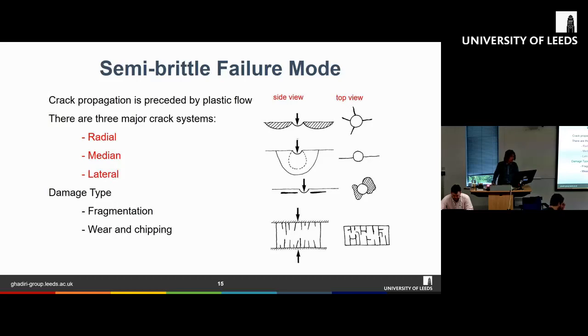And the third type of crack system is called the lateral cracks. Basically, this type of crack is on a surface which is parallel to the free surface of the material, and they chip off and come off from the surface. From the top, it's going to look something like this. Basically, thin layers of material will come off from the surface. So radial and median cracks are responsible for fragmentation because the cracks go deep into the sample and cause the material to fragment, whereas lateral cracks are responsible for chipping and wear of the material.